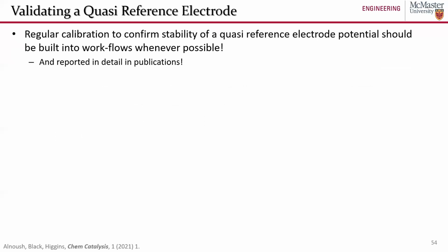So how do you validate these quasi-reference electrodes? Just like any reference electrode, regular calibration is so important. We want to make sure that these quasi-reference electrodes have a well-defined potential and that it is stable over the course of measurement. And that's one thing that's missing in a lot of scientific papers I read that use quasi-reference electrodes: they don't provide much in the way of details of how they calibrate, how they validate, and how they use their quasi-reference electrodes. So if you are using quasi-reference electrodes and you're writing a paper, make sure you put in all the details, because I think that's really important for other researchers to understand the implications of using a quasi-reference electrode, and also to be able to replicate your work reliably.